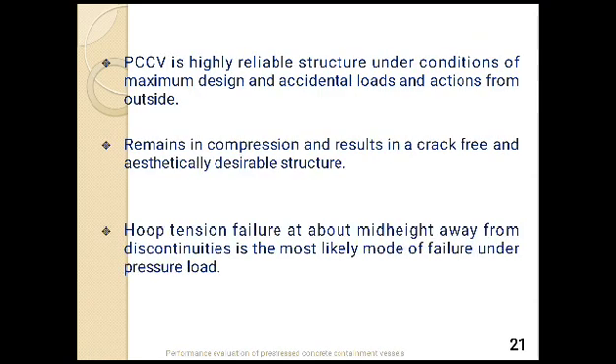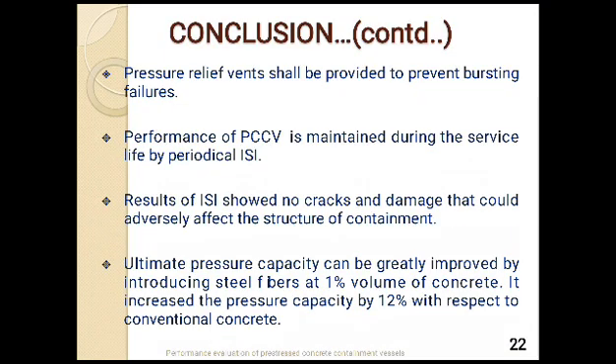Now coming to the conclusions. PCCV is a highly reliable structure under conditions of maximum design and accidental loads and actions from outside. It remains in compression and results in a crack-free and aesthetically desirable structure. Hoop tension failure at about mid-height away from discontinuities is the most likely mode of failure under pressure load. Pressure relief vents shall be provided to prevent bursting failures, and performance of PCCV is maintained during the service life by periodical ISI. Results of ISI showed no cracks and damage that could adversely affect the structure of containment.